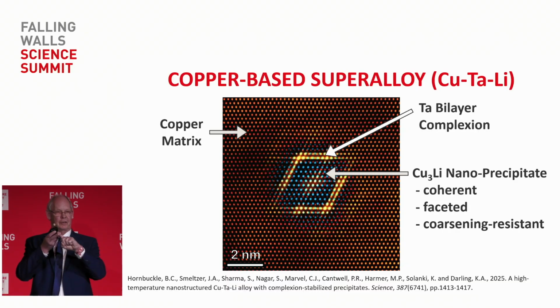So it's like it's enclosed, safe almost, as it were, where it's encapsulating that phase of Cu3Li. The properties of this material are quite amazing. First of all, its creep resistance is very comparable to nickel superalloys. It's about 6 orders of magnitude or more higher than the creep resistance of copper without the tantalum lithium. Its strength is about 1,000 megapascals, which is the order of the strength of many steels.